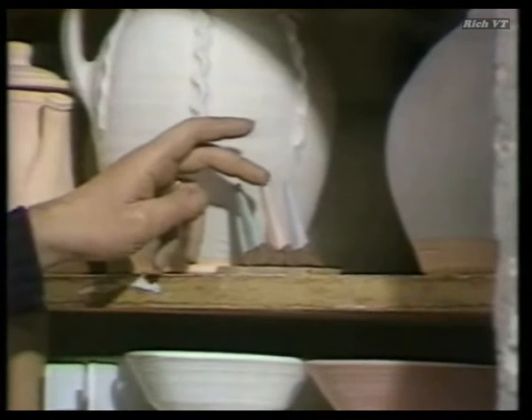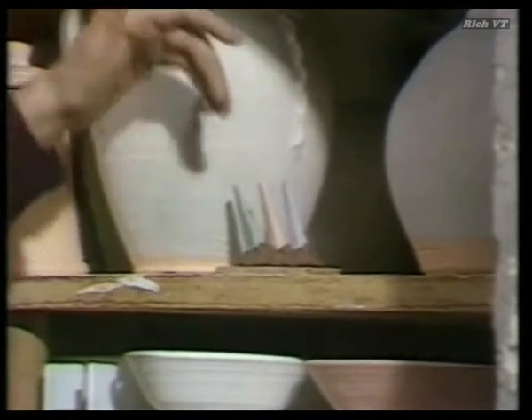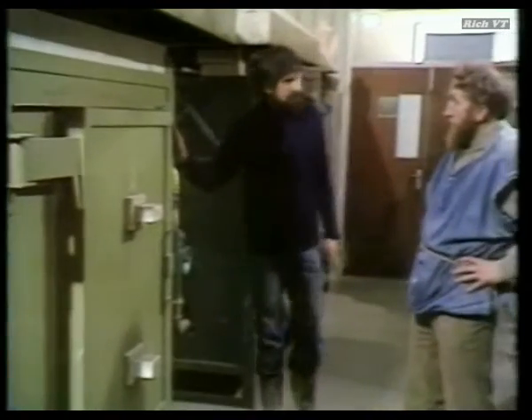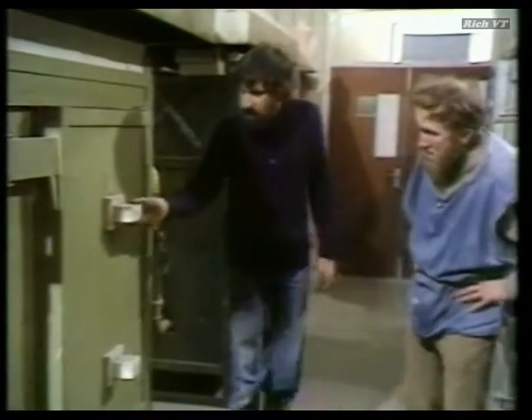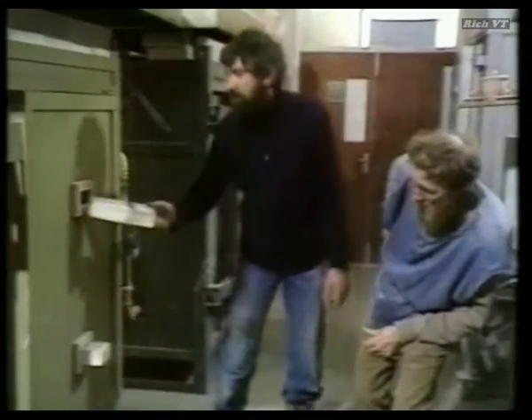The middle one's a 1280 cone. That tells us that we're just where we want to be. And the last one acts as a guard. We want that one to remain standing so that we don't overfire. This kiln's been firing for about 4 hours now. There's about 6 or 8 hours to go. Yes, it's quite a long way to go yet. But have a look and see what temperature it's at. Yes, you can see that the cone in there that's bending indicates that we're at about 1000 degrees centigrade. The other cones will bend later on, of course.